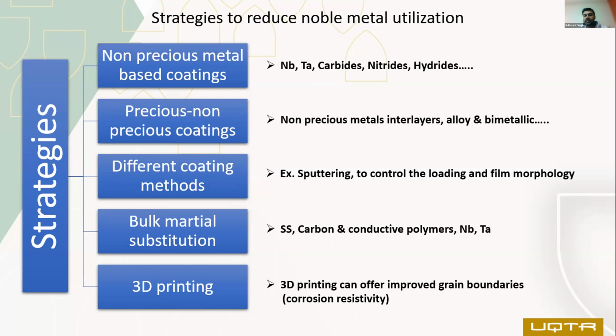So we have benchmark data with platinum, iridium, gold and ruthenium, but we don't have that much research data using niobium, tantalum carbide, and hydrides. So still, it requires comprehensive, systematic research. And if we use these metals as interlayer, bimetallic, or alloy form mixed with the precious metals like platinum and gold, they can improve the corrosion resistance further and eventually reduce the precious metal usage.